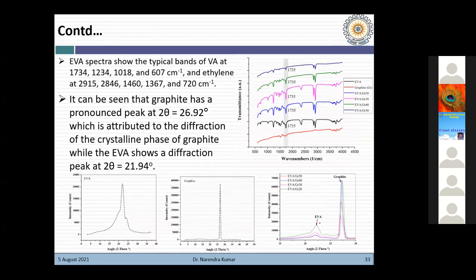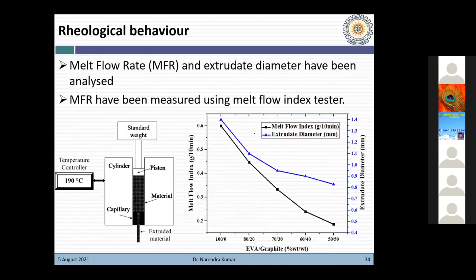You can see the EVA and graphite peaks are available in the XRD spectra. It means the graphite was homogeneously spread across the polymer matrix. After characterization of the material, rheological behavior was also tested. We tested the melt flow rate and the melt extruded diameter, because this is very important in 3D printing. We all know a polymer swells when it is extruded from the nozzle, so we quantified the extruded diameter for different temperature ranges and different compositions. To quantify the melt flow rate, we used a melt flow index tester. So these are the results.